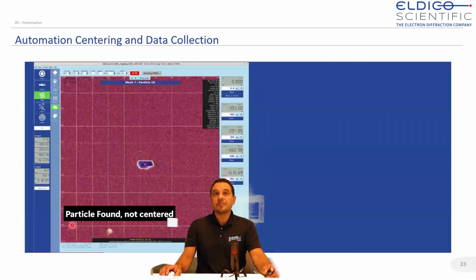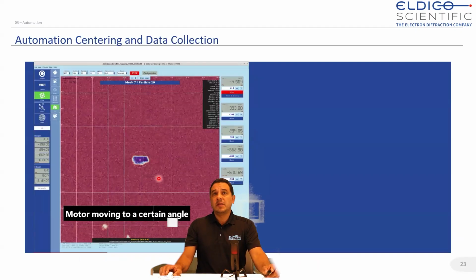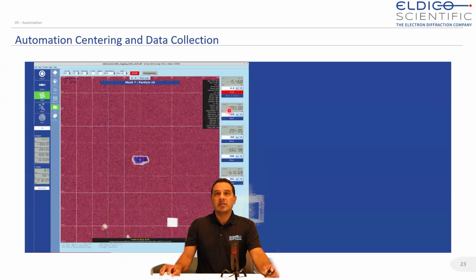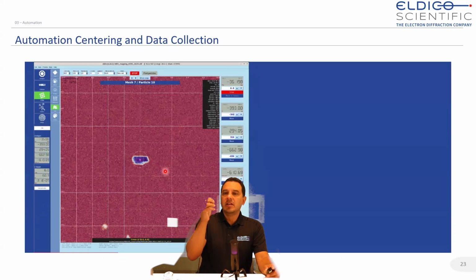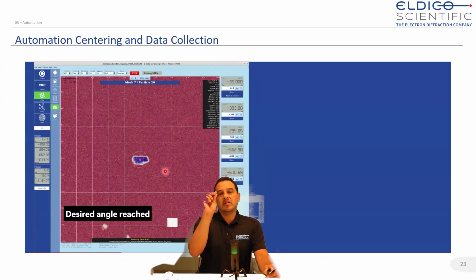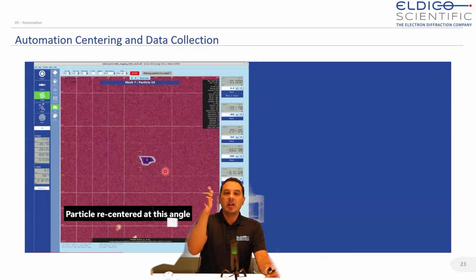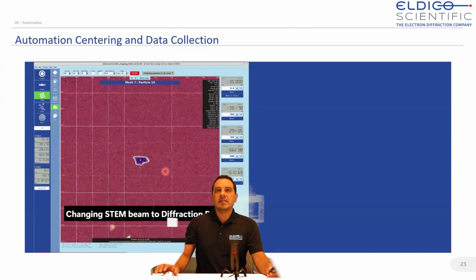And this is where the ELDICO ED-1 device has a difference compared to all other systems available in the market. So now in this video, I'm showing you the process of centering, which this particle has been basically selected automatically. The machine would center at 0, then it would move to a certain degree, which we give, in this case, 30 degrees, and it would take another STEM image. So like you do in X-ray crystallography, when you center your crystal, you put it at a certain position, you take a video of that, you try to put it in the center, you rotate to a certain position and center again. And with that, you align your crystal during this rotation. This is exactly what we do.